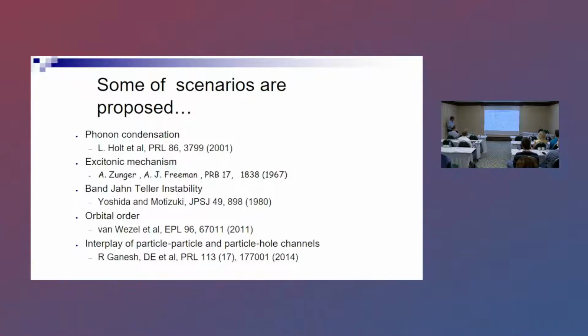And for a very long time this was considered the main idea behind this material. There are several theories which try to explain the origin of the charge density wave. One is just phonon condensation. This is just a normal structural transition: we have some structure at low temperature, then increasing temperature gives motion of the atoms. Therefore, because of this entropy, another structure may be more preferable.